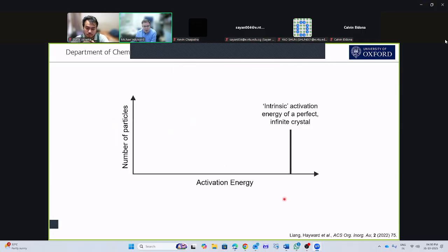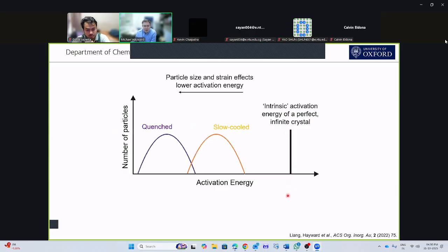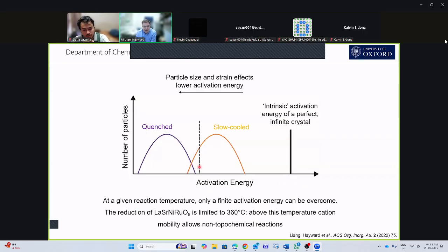And so what I could do now is plot out the activation energy range of different samples. So we could start by thinking about the intrinsic activation of the system, if we had a perfect infinite crystal. And then we could think about our slow cooled and quenched samples, where having a finite particle size and having a finite non-zero strain will then lower the activation energy of that reduction process. And what we're saying is that the slow cooled sample has lowered the activation energy less than the quenched sample has. So that if I perform my reaction at this energy here, you can see I can get all of the quenched sample to react, but only a small subset of the slow cooled sample to react. And so this is how the texture, the particle size and strain in a material can modify its reactivity in topochemical reactions.